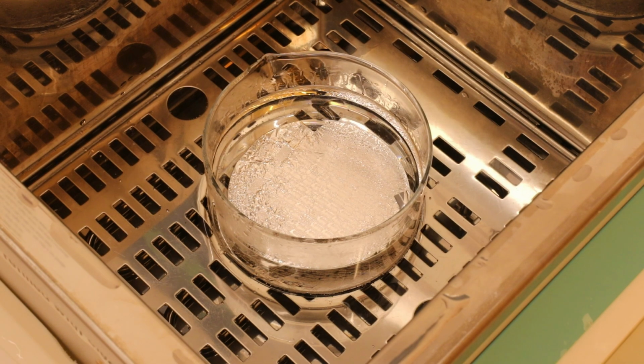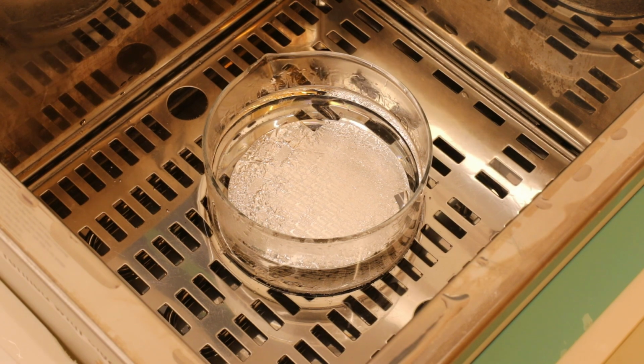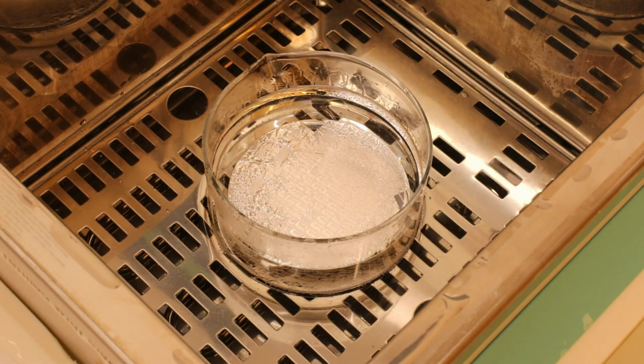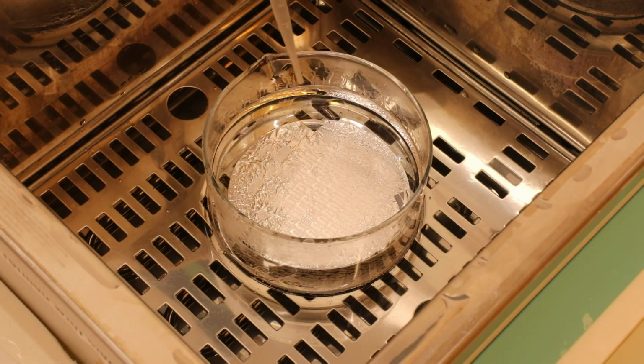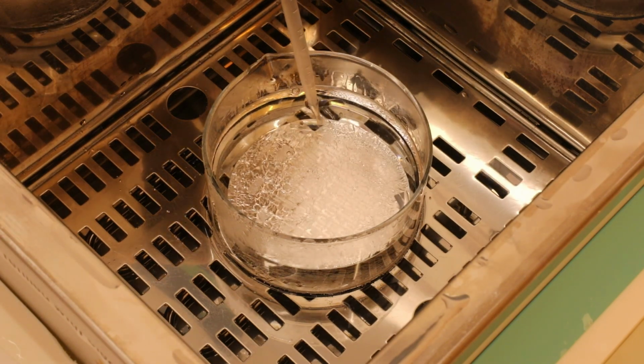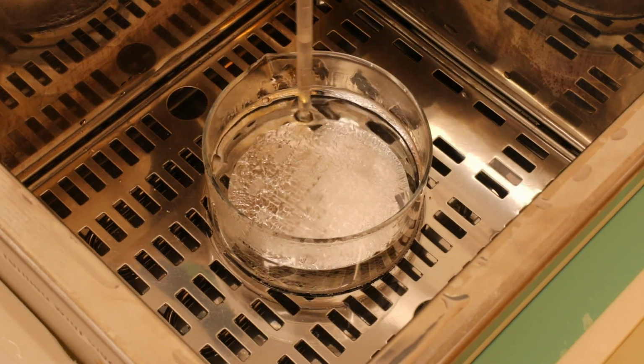Okay, now you can see that the metal surface got a bit bubbly. That means that the resist remover has had enough time to seep through the openings in the pattern resist, so we can probably start the lift off. To help that, I'm going to introduce some liquid flow with my trusty pipette, and hopefully the metal will get a hint and leave.